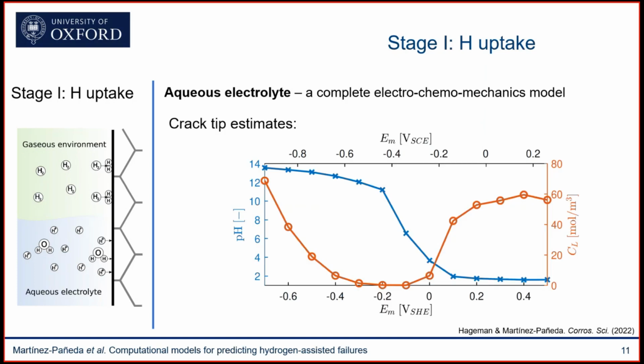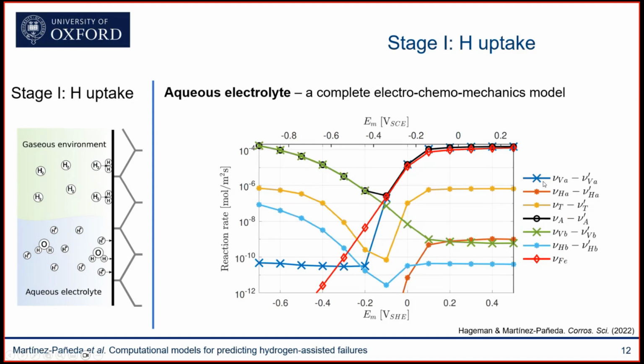And you can see here predictions of crack tip estimates of hydrogen uptake as a function of applied potential. Here I'm changing the applied potential, and you can see that it effectively shows the trend that we expect from our embrittlement predictions. We know that metals embrittle at very low applied potentials, and there's also a dwell in an intermediate region, and then we have an increase again in embrittlement susceptibility. So everything looks good, and not only can you do this, but you can also gain fundamental insight into what's happening, so you can compare the competition between the different reaction rates happening in your material.